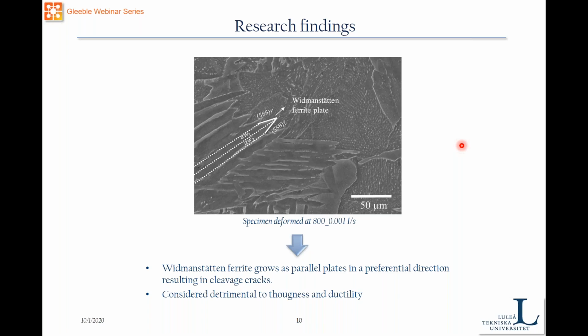Widmanstatten ferrite is a phase that grows in parallel plates in a preferential direction in the previous austenite grain, or it can also grow from allotriomorphic ferrite. But it has been demonstrated that it results in cleavage cracks of the material. These plates work during deformation, the dynamic deformation, as a preferential site for crack formation to occur. So this phase was considered one of the reasons why the material is susceptible to crack formation.